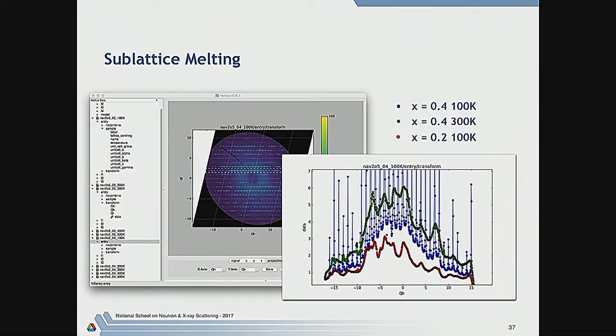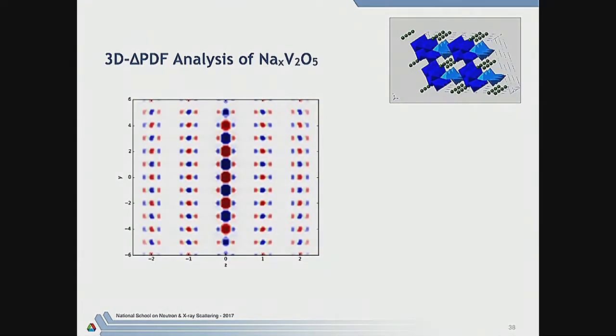Okay, so how do we model this? Well, it turns out we don't have to. If we simply do the Fourier transform of the three-dimensional data from Q space back into real space, we now have sets of interatomic vectors which only represent deviations from the average structure. This is a symmetric log plot in real space. By symmetric, it means that we have positive and negative values. If it's red, it means it's greater than zero. If it's blue, it means it's less than zero. And these all represent vectors, particularly in the sodium sublattice, which deviate in probability from the average structure, which we know is completely disordered. The average structure is just a random occupation of sodium.